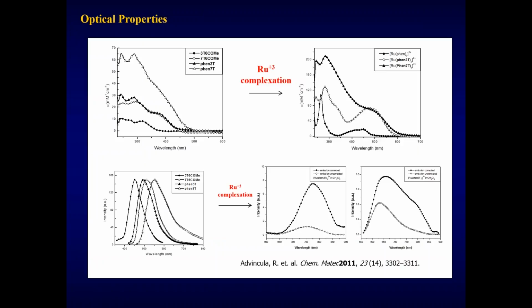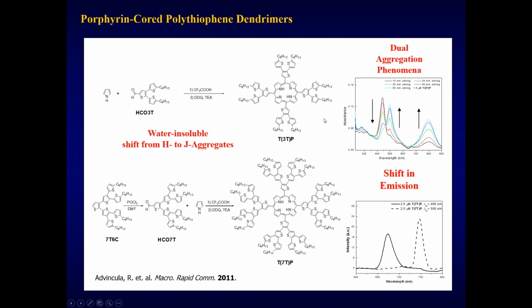In this case, we can complex it with these two groups already present to come up with various structures, which then become evident in terms of their reduction and oxidation states, which we observe by CV, to differentiate between these different types of ligand packing. On the other hand, we can control the absorbance as well as the fluorescence shifts based on the concentration and the type of ligand, showing different types of packing behavior based on the aggregation, as seen by this isosbestic point with different pH.